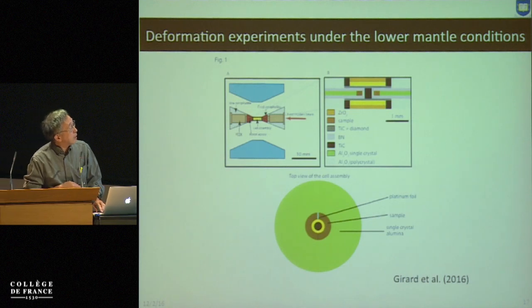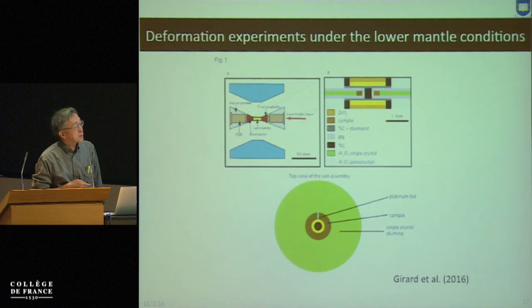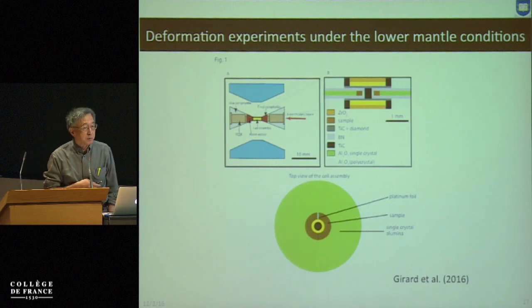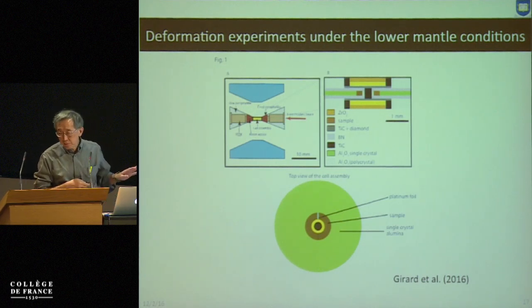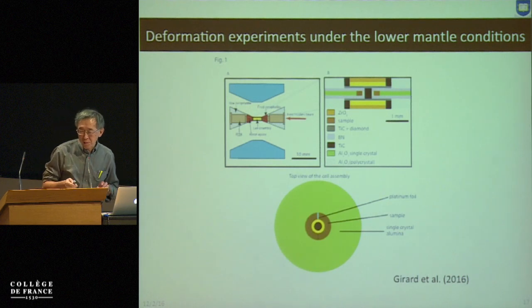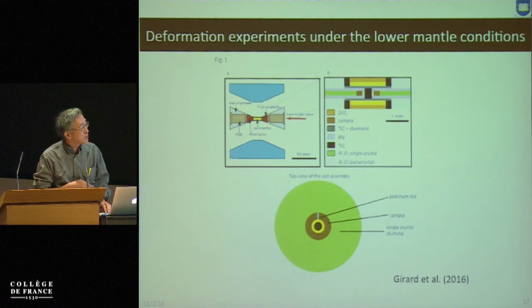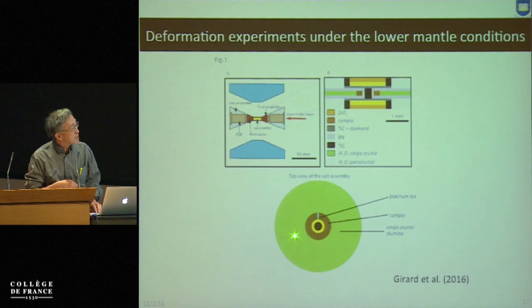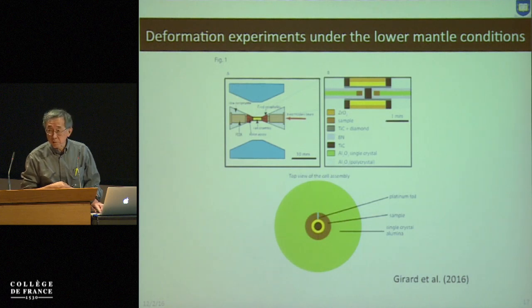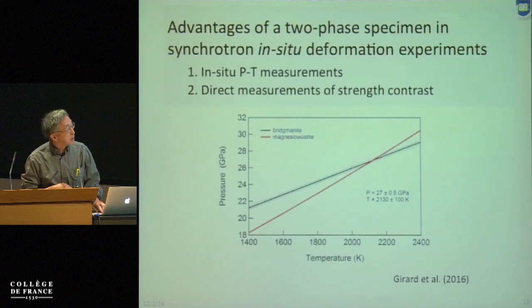So lastly, I'd like to briefly mention how we did the first deformation experiment at lower mantle conditions. Extending conditions to the lower mantle, I tried several times without success, but eventually we realized that there's a pressure gradient inside of this sample chamber, so we put in a small sample, and then we were able to deform a mixture of bridgmanite and magnesiowüstite to a large strain of about 100%.